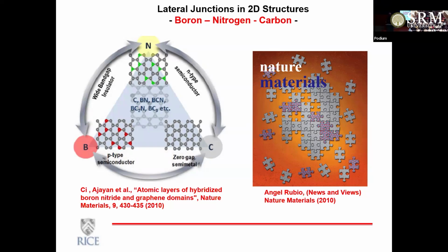Now, carbon, if you take a single component, carbon, you already know graphite, graphene, diamond, all these elements also exist in cubic form. So hexagonal gives you this 2D layer, cubic gives you the three-dimensional structure. So carbon has the variety, right? You have the graphite and you have diamond. Boron nitride, the two-component system, is also very interesting. It also has the hexagonal form and it has the cubic form. In fact, the cubic form is very difficult to make, and we actually have a project trying to do that. So cubic boron nitride is also possible, right?